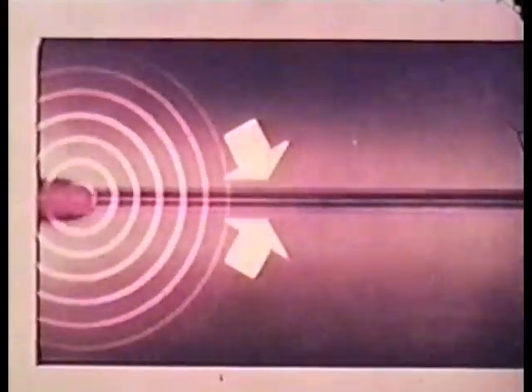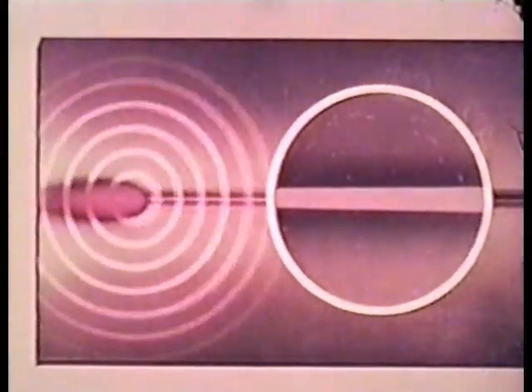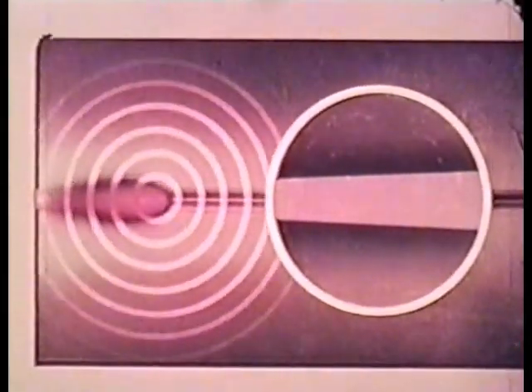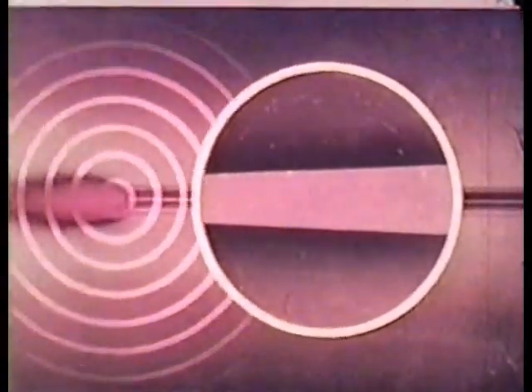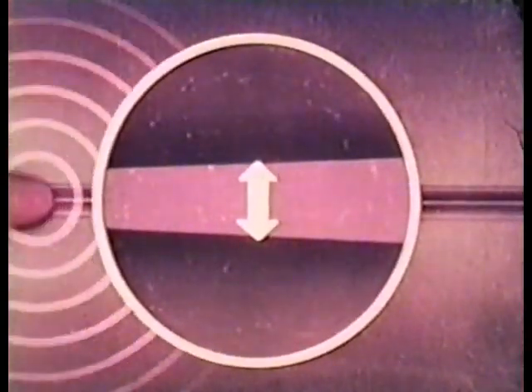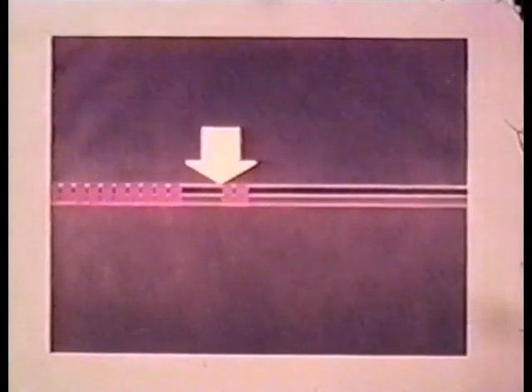When a continuous weld is required, we can control distortion if we first understand how expansion affects the plates. Notice how expansion from the heat of the weld along the edges causes the plates to spread, as shown in the magnified circle. As the weld progresses, the spreading continues, and the plates become locked in this position by the cooling and contraction of the weld metal. Welding speed will determine the amount of this spreading action, but we can control this action and prevent distortion by the use of backstepping, whereby each successive bead is laid from right to left, but the direction of your welding progresses from left to right.